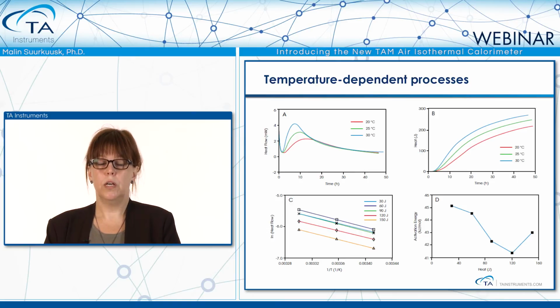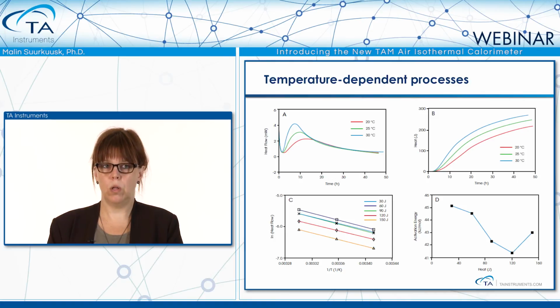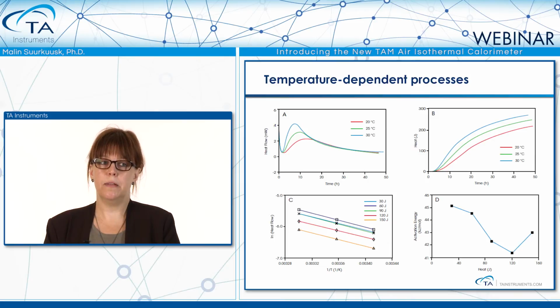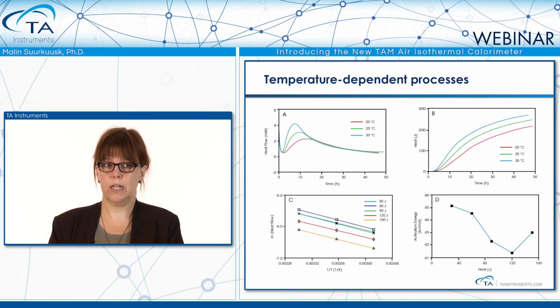For example, you choose after 100 joules evolved heat, and then you go in the B plot to see at which time I have reached 100 joules. And then you can go in the A plot and take the heat flow rate at that particular extent of the reaction. The heat flow at this extent of reaction can then be plotted in an Arrhenius relationship, which is in the lower left curve.